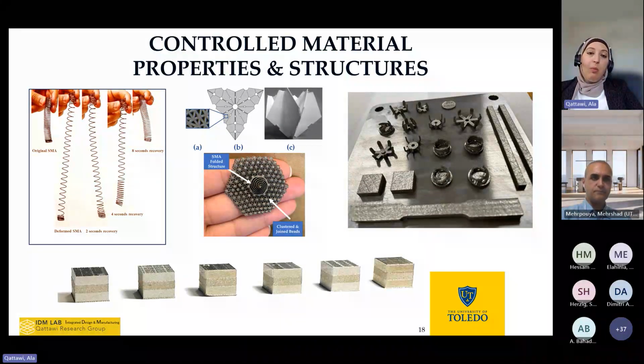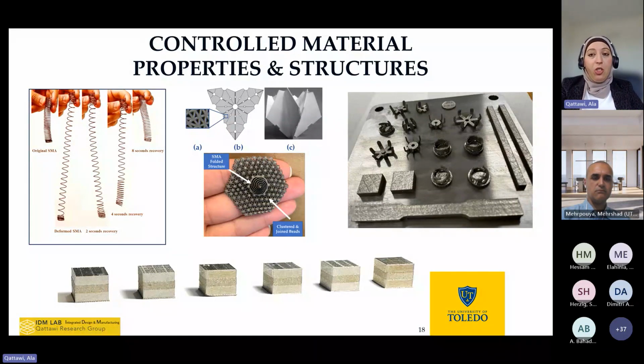And these layers can be controlled. They can be one layer of like 20 micrometers, or even larger because of the laser powder bed fusion capability. So basically the control of the thickness is also not an issue in laser powder bed fusion. So eventually this opens doors that we can leverage, like different structures that we're not able to produce, not just because of the complexity, but because of the microstructure scale that we can produce now.